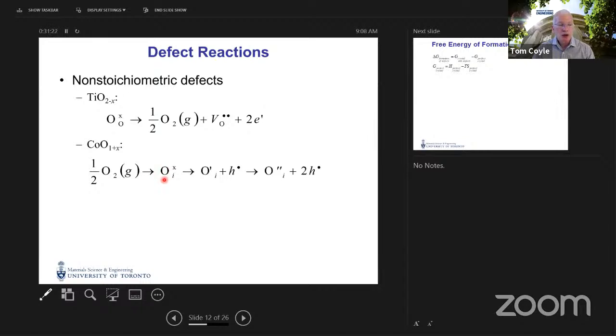So initially it's an oxygen atom with no charge. And so as that oxygen sits on the interstitial site, its relative charge is 0. Now that interstitial oxygen may steal an electron from the valence band in order to attempt to complete its outer electronic shell. And so when that oxygen interstitial steals that electron, it now has a negative charge on a site which normally doesn't have a charge. And so we have a relative charge of -1, and we create a hole in the valence band.